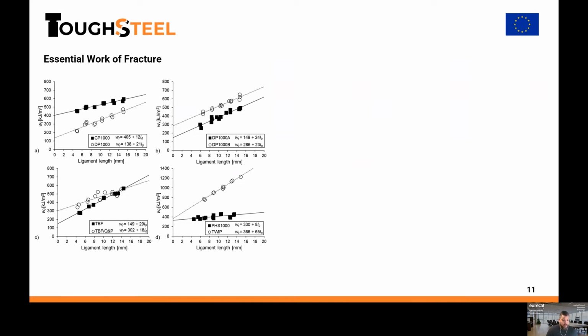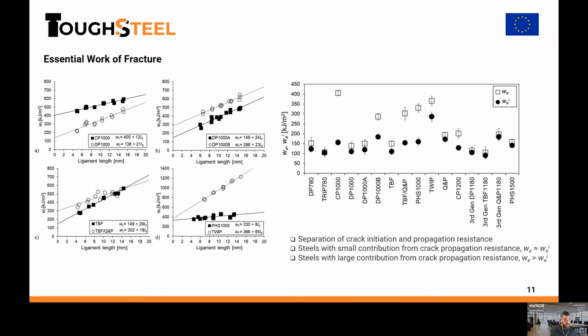Of course, the method has been used a lot over the last years, mostly in polymer films and also in other ductile metal sheets, aluminum alloys, ductile steels. But we have been working a lot with application to advanced high strength steels to understand these different fracture behaviors. Now, as I said, an interesting part of the essential work of fracture is that it allows us to separate the contribution of initiation and propagation, the essential work of fracture being related to propagation, but we can also obtain this initiation toughness.